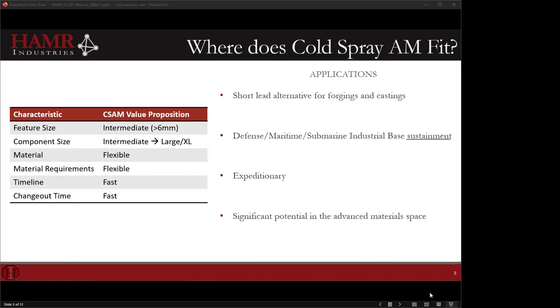So drilling down into it more, where does it fit? Consolidating that eye chart into a digestible table here. Feature size, we're looking at parts that have minimum feature sizes, ideally greater than 6 millimeters, to reduce the amount of machining that we need to do. Component sizes, it can do any component size, but where our bang for the buck is when we start to get to intermediate to large and even extra large components.